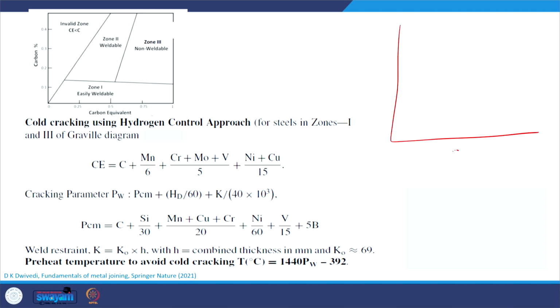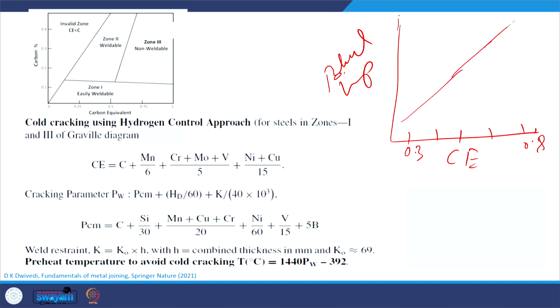Usually we have the direct relationship between the carbon equivalent, ranging from 0.3 to 0.8, and here we have the preheat temperature requirements. So, this preheat temperature increases continuously with increasing the CE. So, this direct relationship is particularly used for certain kinds of compositions.